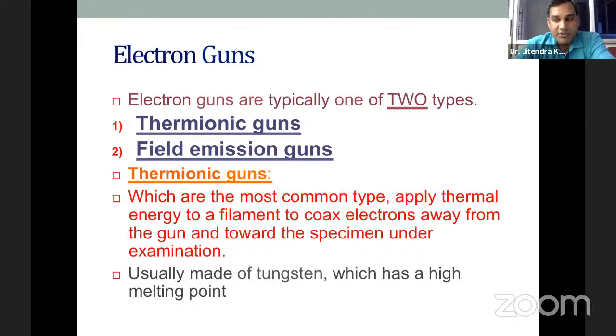So you have seen two types of SEM images. Nowadays SEMs use thermionic guns or field emission. Field emission gives you better surface topography than thermionic. Why? Because in the thermionic system, which was used previously, the energy of the electrons is not that high, so the scattering of secondary electrons is not that prominent, and they cannot be captured perfectly by the detector.